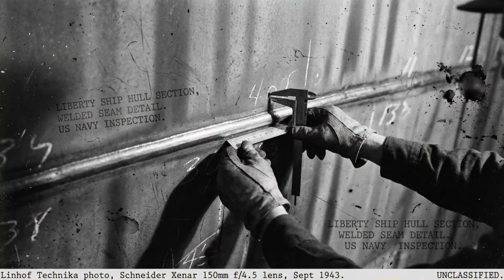Tipper demonstrated that the fractures did not originate in the welds, as many had assumed, but in the steel itself. The mild carbon steel used in Liberty ship hulls underwent a dramatic transformation at low temperatures. Above a certain threshold, the steel was ductile, able to flex and absorb energy without breaking. Below that threshold, it became brittle, prone to sudden catastrophic failure, like glass shattering under impact.